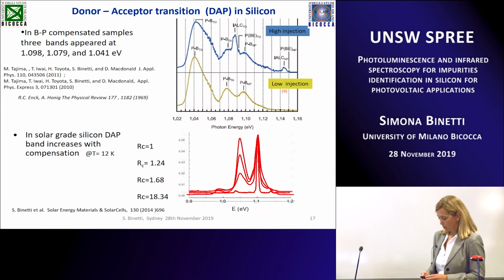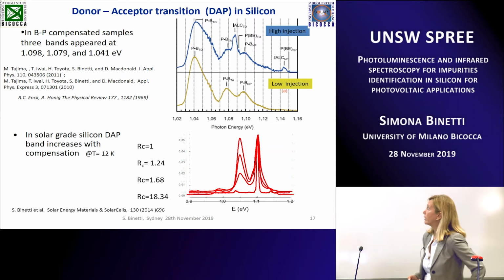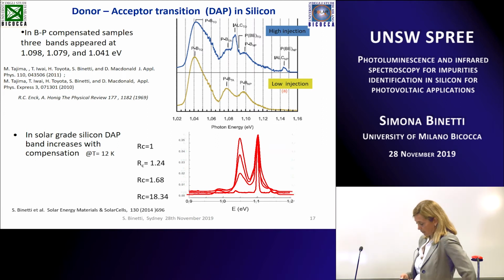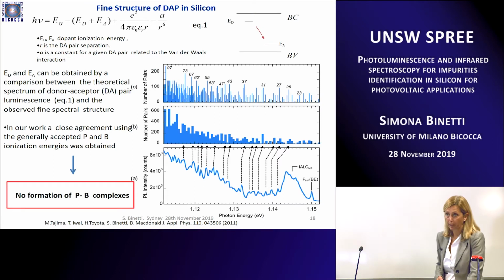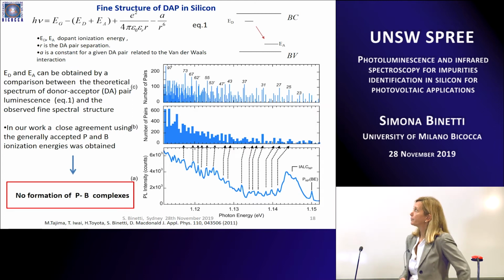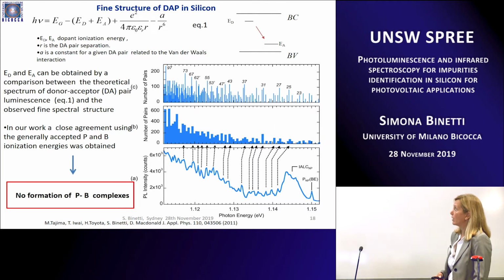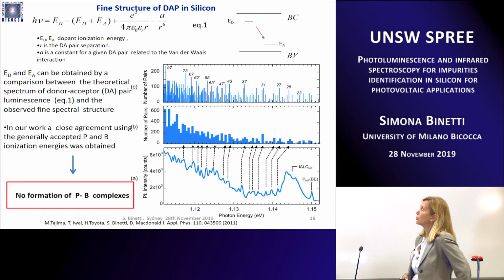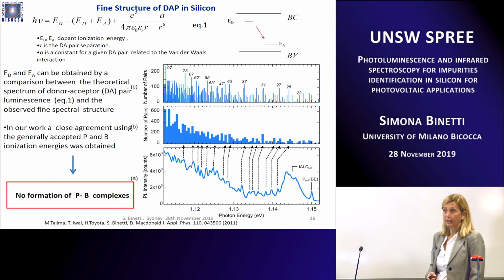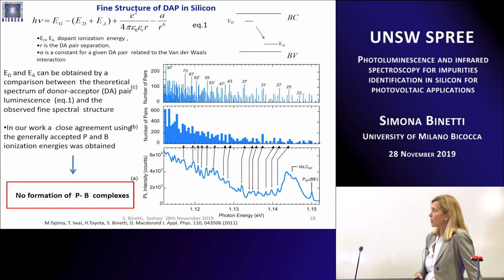If you perform a much more different analysis of this band, not just looking at the intensity and the position, but checking the fine structure of this band, we can have some information about the dopant ionization energy, or if they are not dopants, the ionization energy of this level closer to the respective bands, conduction or valence band. Because there is a relationship between the position and the dopant ionization energy and the Coulomb interaction between dopants at low temperature. So by making this analysis, we succeeded to define that no boron and phosphorus complexes can be formed in your material.